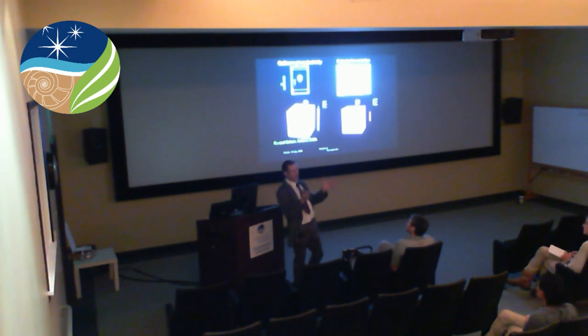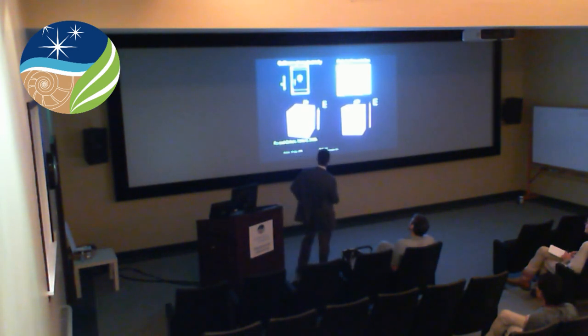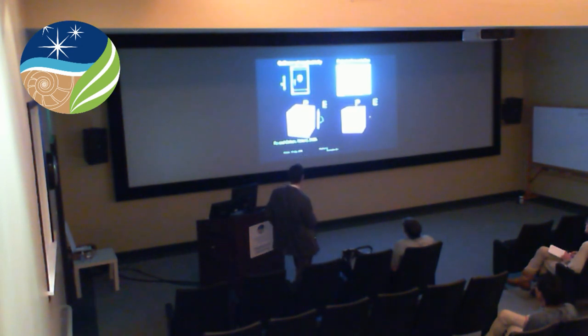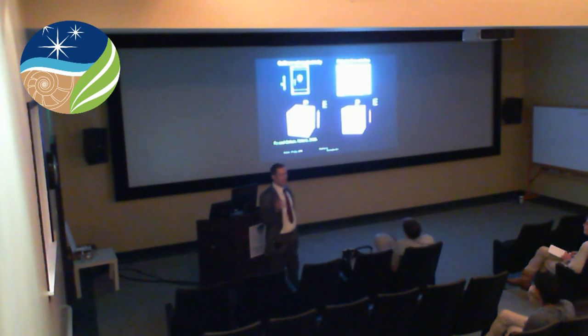And in fact, for technical reasons, in an experiment, this is, as Roger can explain to you, the easy measurement to make. If you think about putting electrodes on a disk, you put electrodes on the face of the disk, you don't put them on the edge of the disk, it's kind of hard. So this is the easy measurement to make, and you have an electric field, and I was going to explain piezoelectricity and ferroelectricity here. Well, maybe ferro is not explained so much here, but this is the strain part, the piezo part. So you see the thing changing shape as a function of the electric field, and what's happening is the dipole moment, the polarization, is changing in response to the applied field. Now the ferroelectric part would be that you apply the field in the opposite direction and you switch the direction here. Okay, that's the only bit that's different.